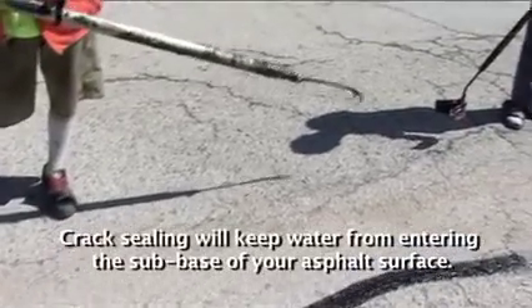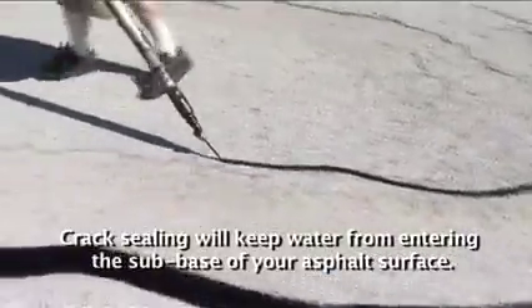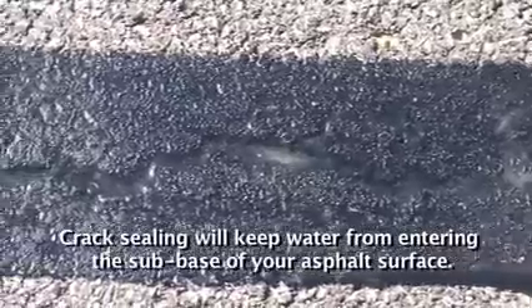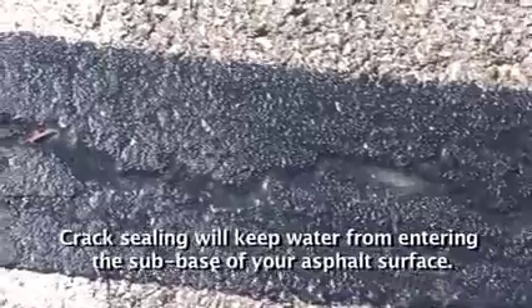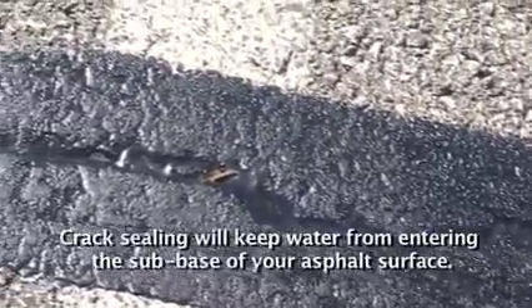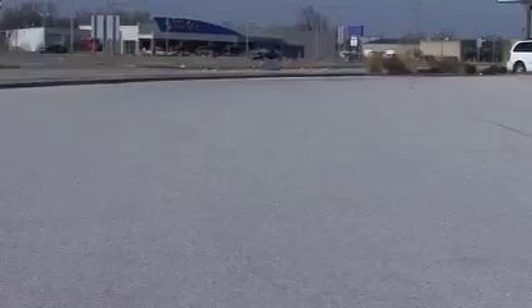We have horrible freeze-thaw in the Midwest. When that water freezes, it pushes up and causes the cracks to open, which in turn causes potholes. So the first form of maintenance is to let people know that simple crack sealing with a good hot rubberized crack sealing material will keep that water from getting to the subbase. Once the cracks are sealed, the asphalt, however, is still porous.